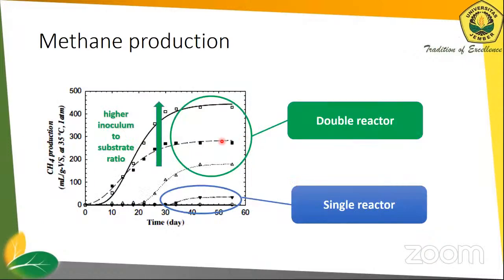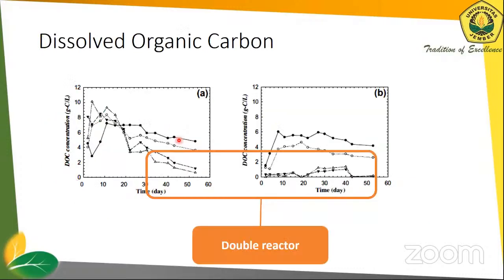We can see that using the double reactor, the methane production is higher, and if we increase the inoculum to substrate ratio, we could also improve the production. Using the double reactor, we could reach about 400 milliliter per gram. And also this is the dissolved organic carbon. Using the double reactor, the carbon, the feedstock material in the media, is consumed more effectively. Only a small amount of substrate remains.